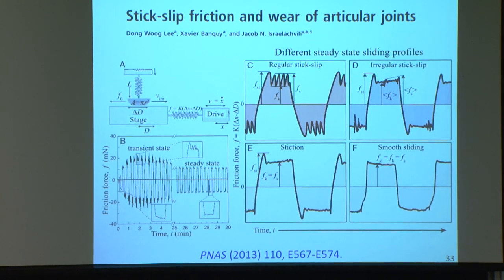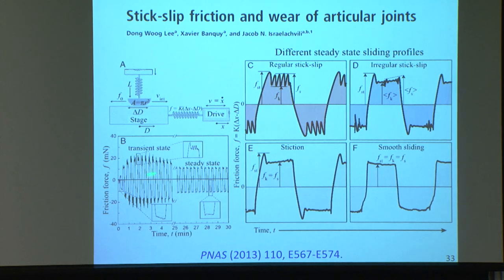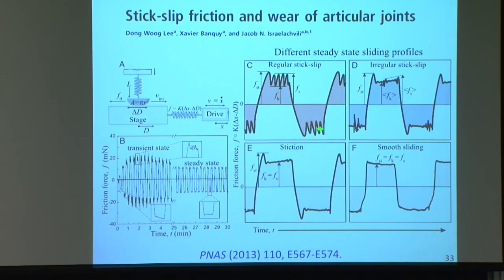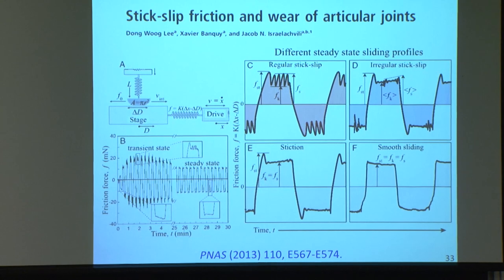And we did some experiments where we investigated this. And we find, sure enough, there's some regimes as we slide back and forth. If there's no stick slip, that's the friction that one measures. You go one way and then the other way. In other cases, there's some very definite stick slip. And you can see that. In some cases, you get what are known as some stiction spikes. They can be quite complex behavior.